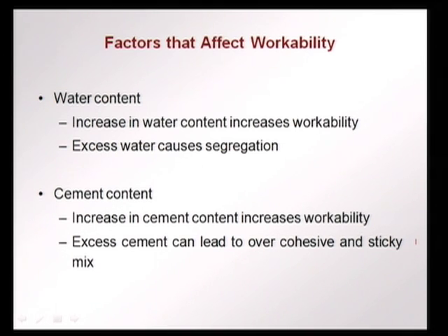What are the factors that can affect the workability of the fresh concrete? Workability is the ability to place, to finish and to compact the concrete. Water obviously helps, increase in water content increases workability. However, higher water content means that strength goes down. If you remember, when we talked about the microstructure, we saw that more water gives rise to more capillary porosity, more voids within the microstructure of the hydrated cement paste, therefore, we do not want too much water. Also, water increases the possibility of chemicals to enter, water to enter in the hydrated concrete, and this could lead to durability issues. In the fresh state, excess water can lead to segregation.